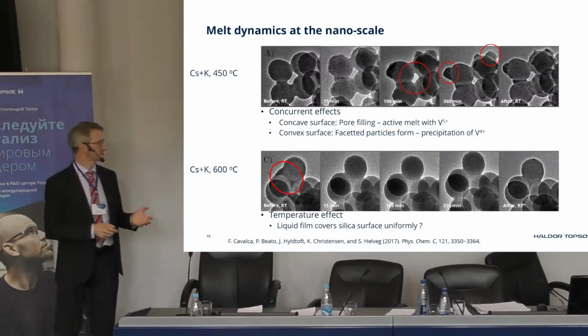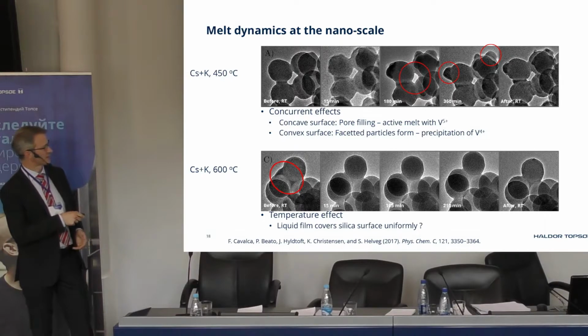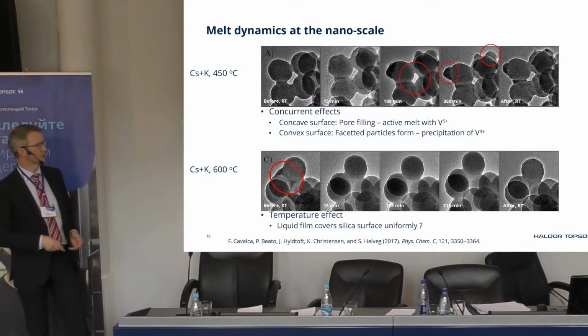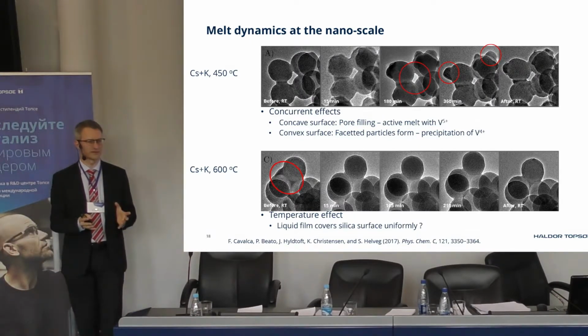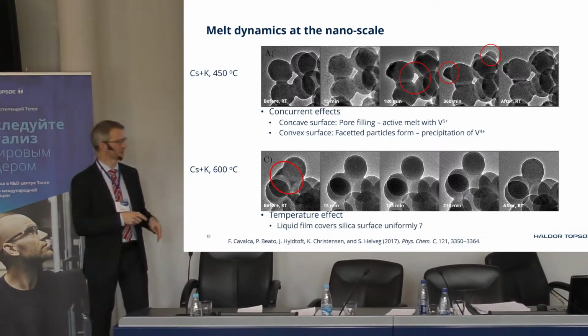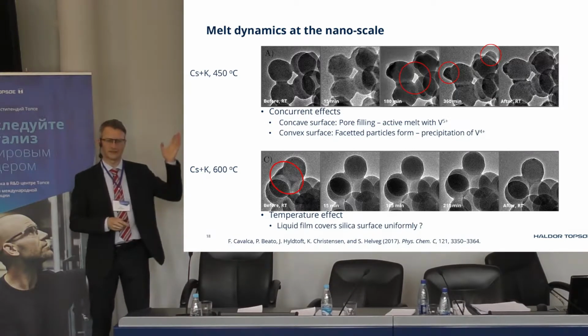If we do the same at a higher temperature, 600 degrees, it's different because we cannot really see all these details, and we think here that the liquid film is actually uniformly covering the silica. It's not disappeared, because if we bring it to 450, we will see the same. So it's still there, but it's more uniform. It makes sense that we don't have the reduction in the precipitation at the high temperature.